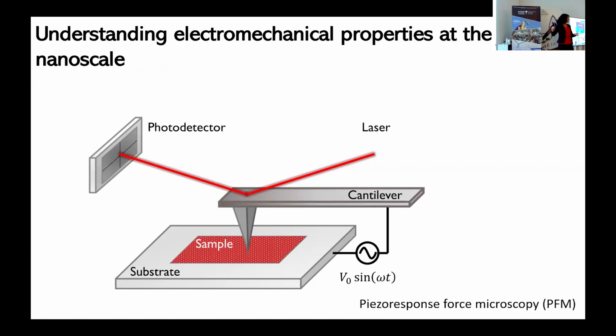Some of you might already be familiar with piezoresponse force microscopy, where we use an AFM tip to apply a field across a sample. And if it's a piezoelectric sample, it will deform because you're applying a field across it. And you can measure that deformation with your AFM, the optical setup. So that's how it works. You apply an AC bias and see whether the surface of your sample is getting displaced at that frequency. The problem is, as you can see, it's a sharp tip.